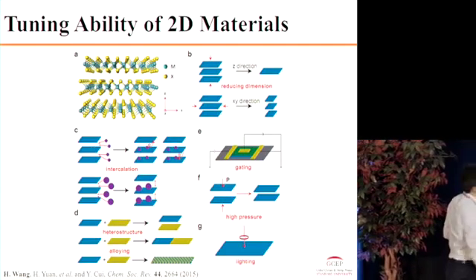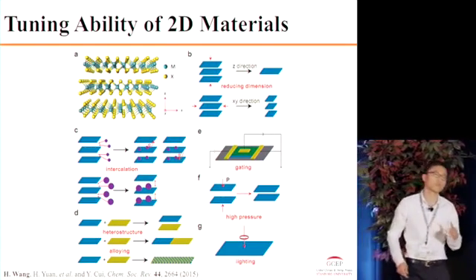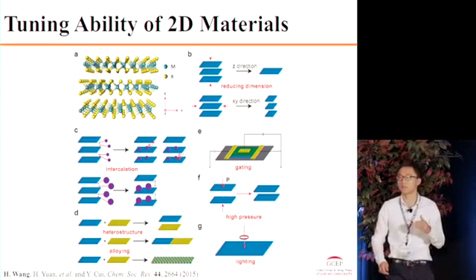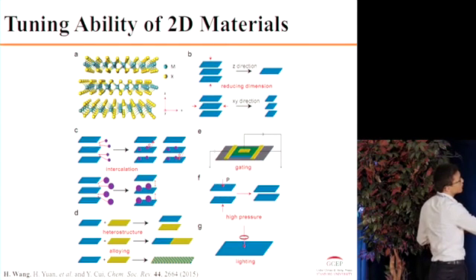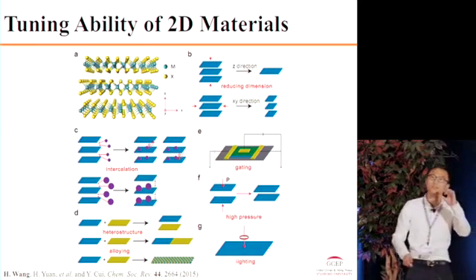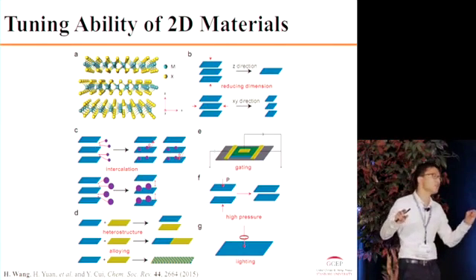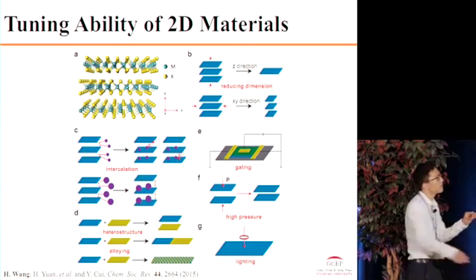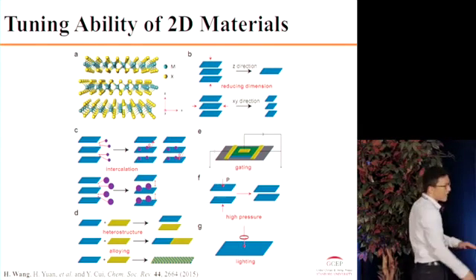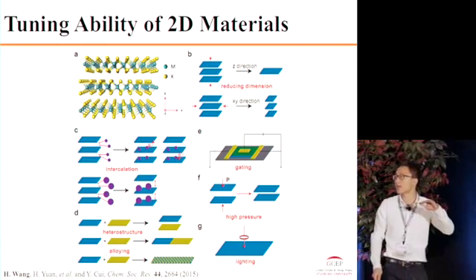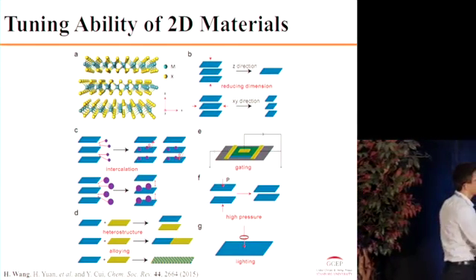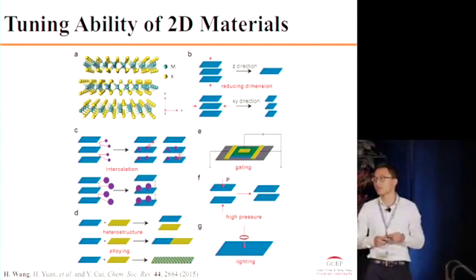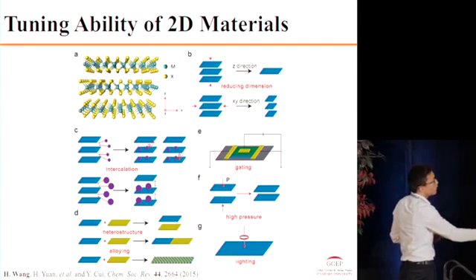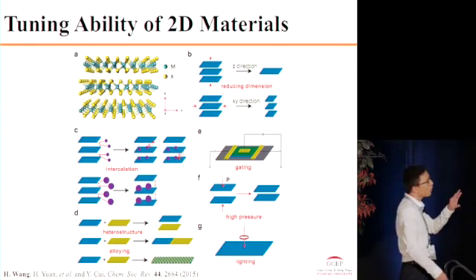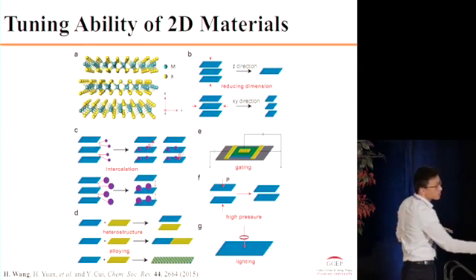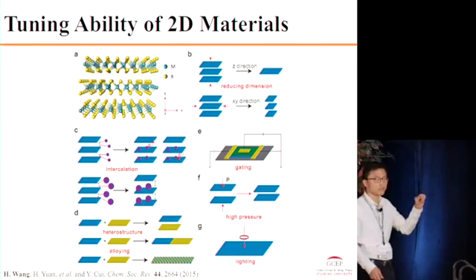The reason why we focus on layered materials is their flexible tunability in material properties. Due to their very unique crystal structure, they have atomic layers with very strong covalent bonding within the atomic layer, but those layers stack along the z direction with very weak van der Waals interaction. This high bonding anisotropy gives us a lot of opportunities, such as reducing the dimension within different atomic orientations, and you can also intercalate a lot of guest ions between the van der Waals gap.